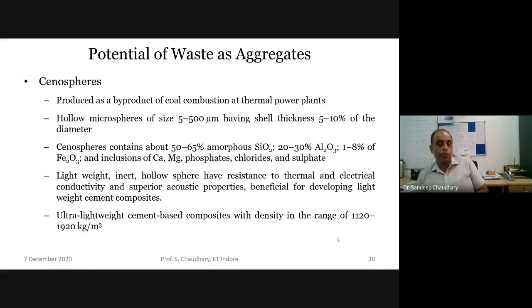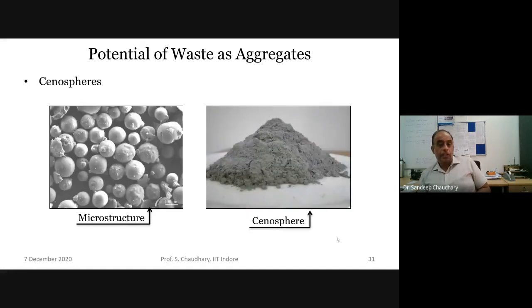So it has high resistance to thermal and electric conductivity, superior acoustic properties, and it can be used for developing lightweight cement composites. So we can make ultra lightweight cement-based composites with a density in the range of 1120 to 1920 kg per meter cube. So that is it. You can see the microstructure. Very spherical particles, and so that is its own advantage.